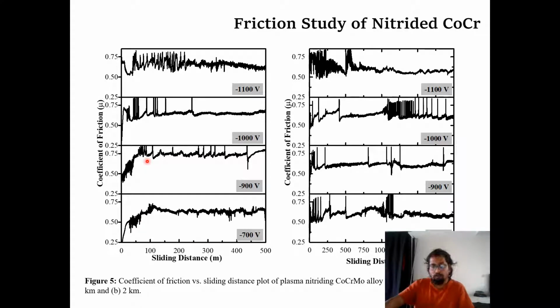The sliding running period over 400 meter was visible for 700 and 900 volt, whereas for 1000 and 1100 volt it was almost zero, which means it starts directly at higher and then starts stabilizing at some point after running for 20 to 50 meter. And most of this waviness represents the damage that happens during the sliding of the surface, because one of the reasons is that these two samples have high roughness as well as their microstructure is in a way that they can break if high voltage, high load is applied. Same goes for the 2 kilometer.